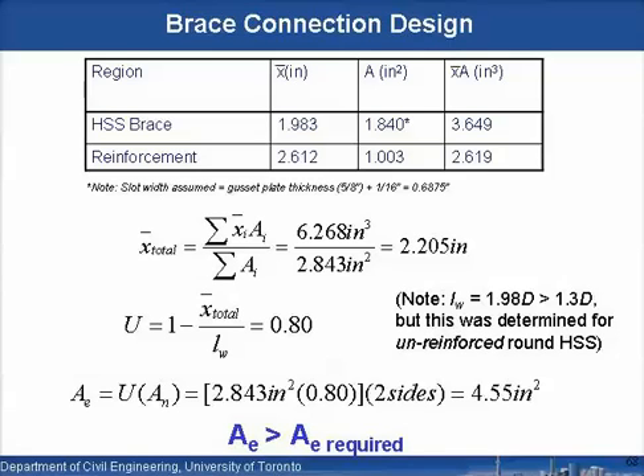So now, having solved for this X bar, the centroid of this half cross section on one side of the plate, we can use this U factor, U equals 1 minus X bar over the length of the weld, X bar over LW, to calculate what the U is, which is the reduction factor to account for shear lag. And we get a value of 0.8. So that means the cross section at the end of the gusset plate is only 80% effective, and there's about a 20% loss in effectiveness there due to this shear lag phenomenon.